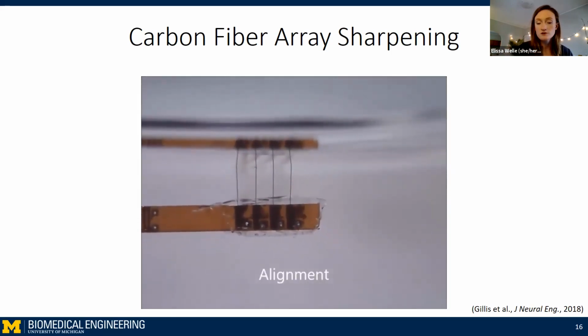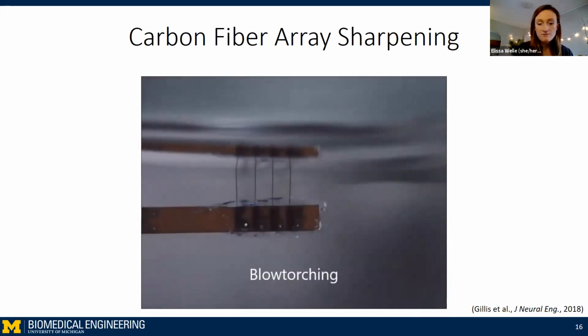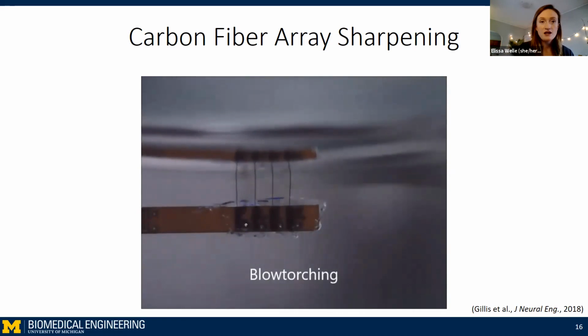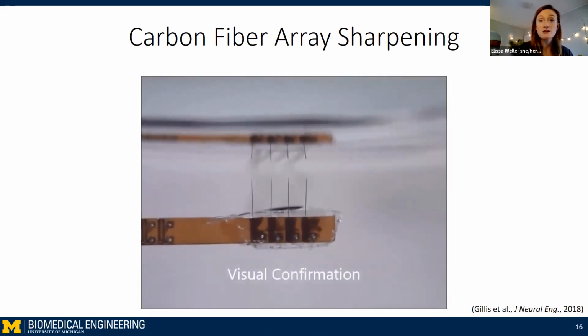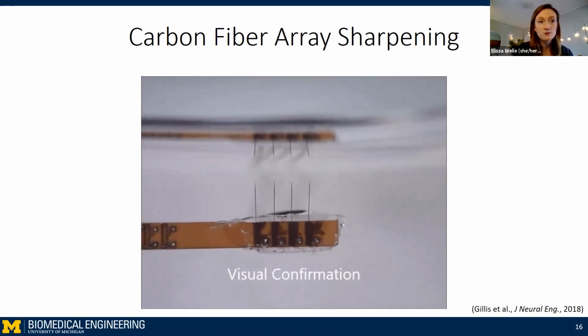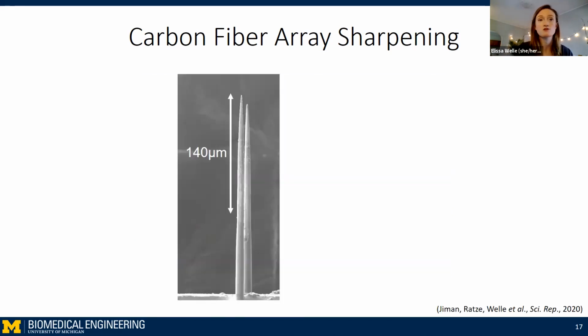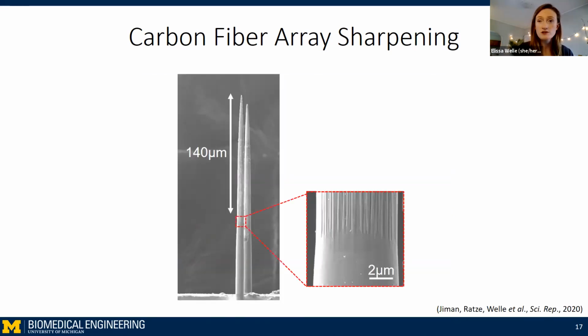And then afterwards, this is the alignment step. And so that's where the wire is moving in response to the flame. And afterwards, you can see a slight tapering in the carbon fiber tips. And so through this process, we get sharpened fibers. There's a really smooth transition between the carbon and the insulation.